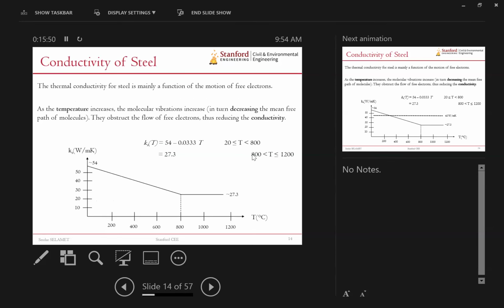So the conductivity of steel starts with 54 watts per meter per Kelvin. So again, watt here is the heat flux. You can think of this as power, okay? But in this case, it's actually energy multiplied by time, divided by meter of length, divided by, again, Kelvin. Of course, you can think of this as Celsius. And that conductivity will drop as we go to higher temperatures, and it will stay pretty much constant after 800 degrees. And I think this range is already a very, very dangerous state for steel to be in. So most of the time we have to keep the temperature of the steel member below 800 degrees in order to have a functioning structure.